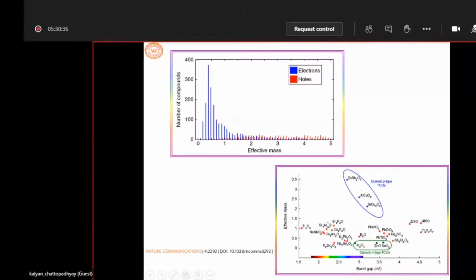Also, if you look at this lower plot, you can find that these are all materials that are N-type conducting, but these are the current P-type conducting materials. You can see there are three prototypes. One is copper aluminum oxide, another is strontium copper oxide, another is zinc rhodium oxide. But look, all of them have much larger effective mass, greater than 2, again indicating that mobility will be difficult to achieve. So then what is the way out?